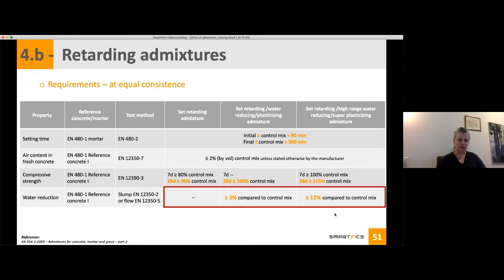It also goes in line with the water reduction. So if you have a standalone set retarding admixture, then you have no requirements relating to the water reduction. And then the same as a dispersing admixture, if it's a set retarder that is also plasticizing, then you should have at least 5% water reduction. And if you talk about set retarding admixtures that are also super plasticizing, you should have in addition at least 12% water reduction.